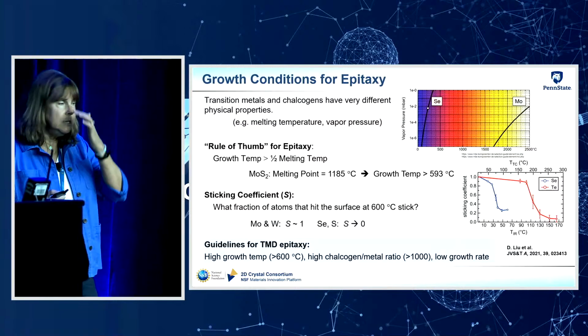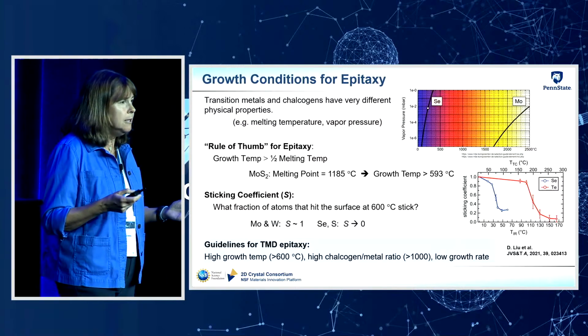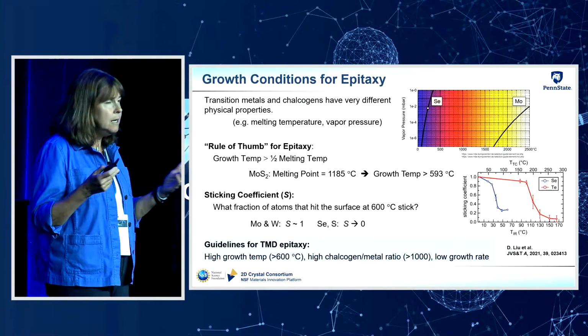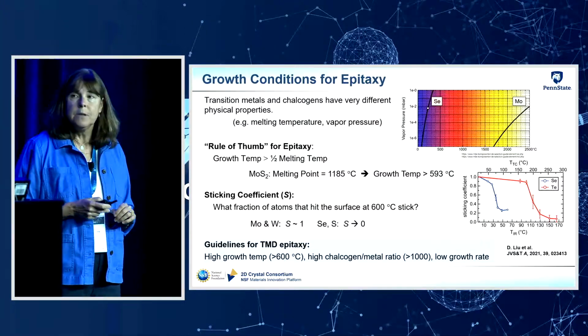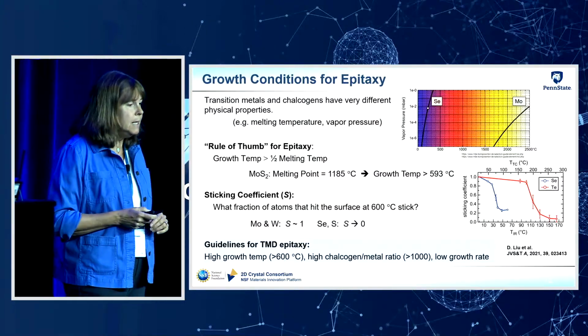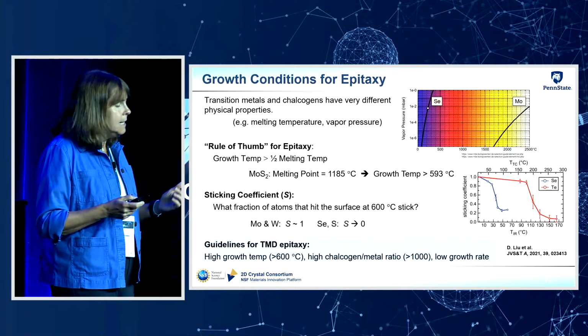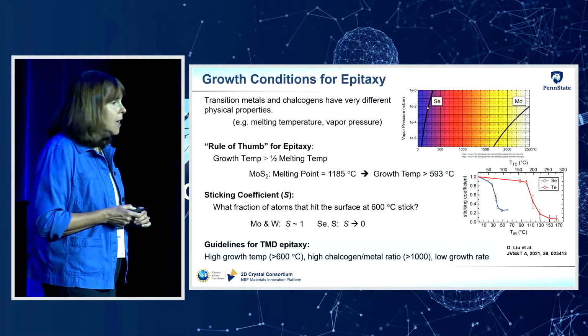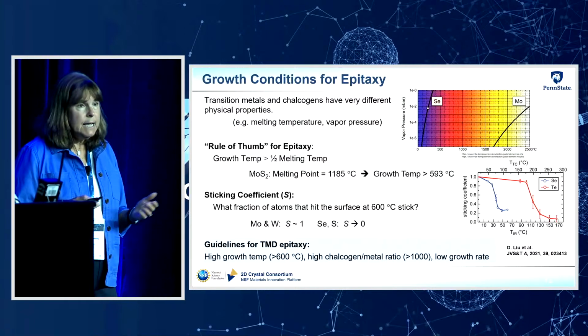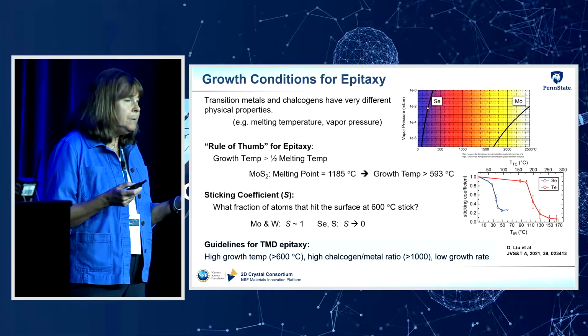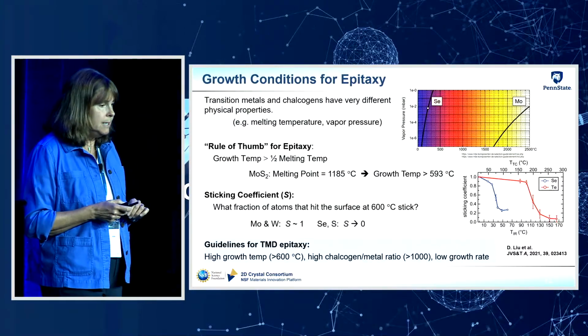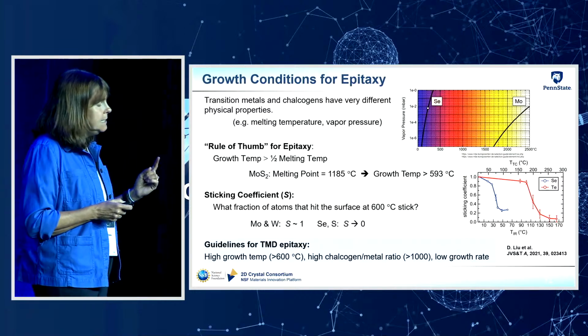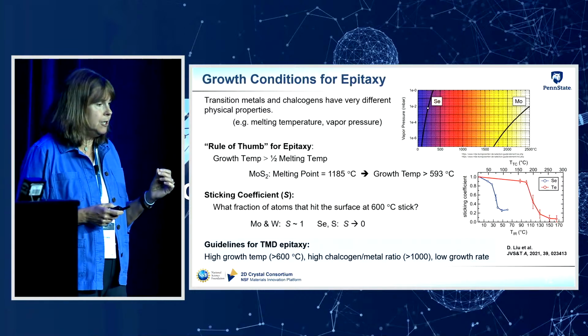And this is based on, you may be familiar with the zone model of microstructure development. So it comes out of that zone model. So if we just consider that for something like moly disulfide, it has a melting temperature of 1185 degrees C. So this indicates that our growth temperature needs to be greater than about 600 degrees C. The final thing that we need to consider is the sticking coefficient.